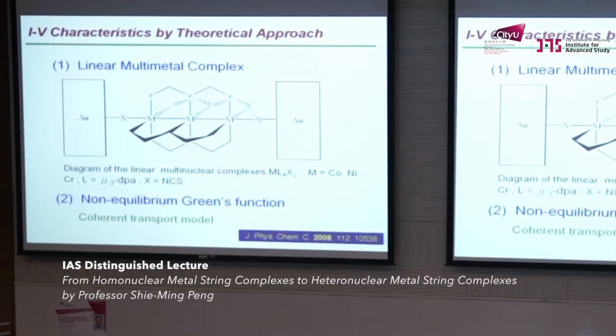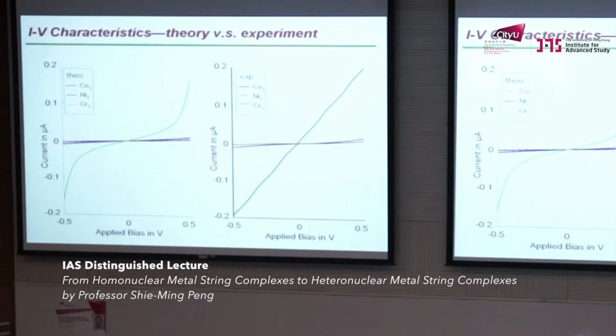Nowadays, we can attach the molecule to gold electrodes, as I mentioned, experimentally, and also theoretically study how electrons transport through the molecule. The right-hand side is the experimental IV curve for chromium, cobalt, nickel. That means chromium conducts better than cobalt, than nickel. Okay? Theoretical modeling shows that nickel and cobalt are quite consistent. The model shows good consistency with the experimental one. Chromium is not so consistent, but in the same order of magnitude anyway, because we only use extended Hückel to treat the molecular orbitals. It's not so satisfactory. But anyway, we get the theoretical model.